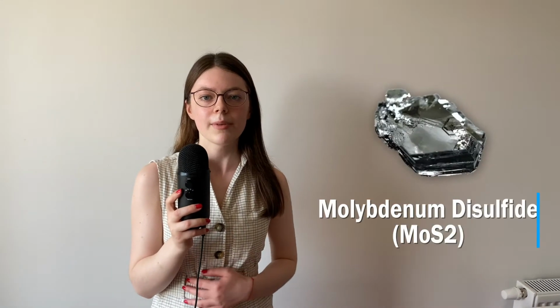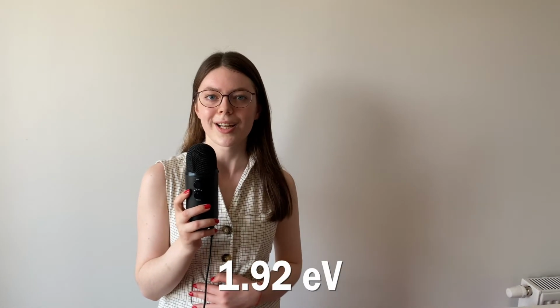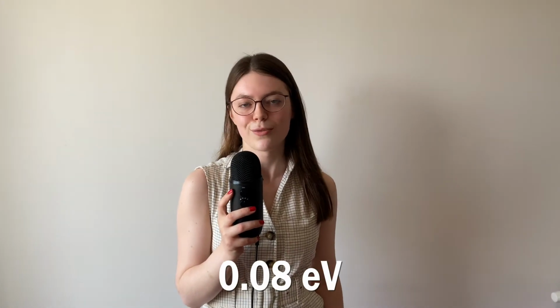Yeah, we need to start looking for a cheaper and more abundant material. One such catalyst could be molybdenum disulfide, with a hydrogen adsorption energy of 1.92 electron volts, which is not close to our desired value of 0 electron volts. It was believed that the catalyst molybdenum disulfide was inactive for HER. However, it was later revealed that at 50% hydrogen coverage, it possesses a hydrogen adsorption free energy of 0.08 electron volts, near the optimum value of 0 electron volts.